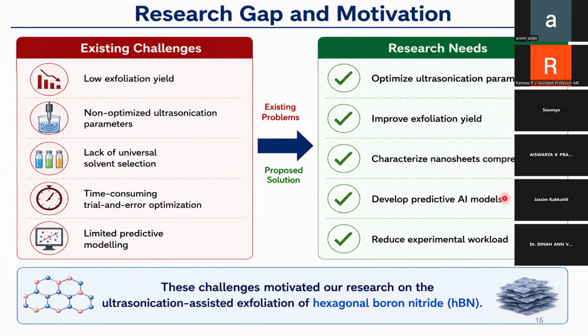Then definitely comes the AI model, where you can have predictive AI models to find out which combination will give you the maximum yield percentage, and the crystal structure integrity likewise. So by utilizing these predictive AI models, you can reduce the experimental workload as well. So, by actually understanding these things, we ended up in the ultrasonication assisted exfoliation of hexagonal boron nitride. And this was the reason behind why I chose hexagonal boron nitride as my material, and definitely the 2D material for the further research. And during my research, I have taken this hBN and I have done this